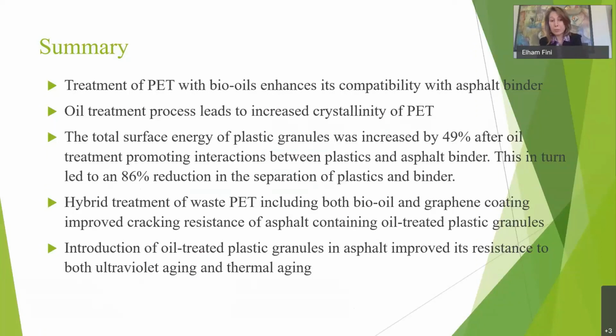And the next step was hybrid treatment, which also showed the graphene coating hybrid with bio-oil coating. It actually helped improve resistance to cracks, especially at low temperature, which is very important in the states that get very cold winters. And overall, the introduction of the oil-treated plastic helped resistance to aging, whether ultraviolet or UV aging from the sun, or thermal. It helped with both types of aging. So it can be a significant improvement in extending the life of pavement, again, provided plastic is compatible with asphalt or cement or construction material and doesn't leach out and leave the construction. Compatibility is key to make sure it performs well and is durable long term.